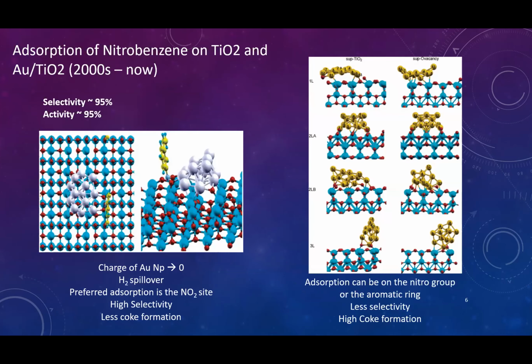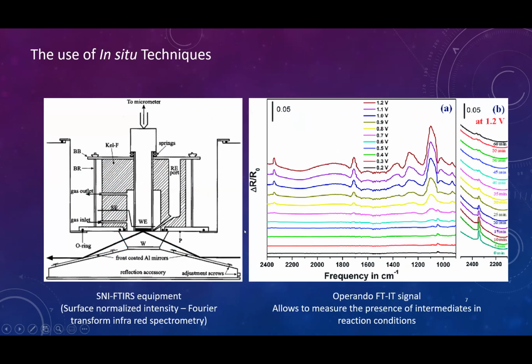So with the development of new technologies, they started using computational simulation. In this case, we can actually see how the catalyst will behave in the presence of our substrate. On the right-hand side, you see the adsorption of nitrobenzene on titanium dioxide can go through different modes, depending on whether we have oxygen vacancies or not. In any way, the adsorption can go through the ring or the nitro group. And when we add gold nanoparticles, the adsorption through the nitro group improves the selectivity and the activity. The use of in situ techniques allowed us to see the intermediates on the surface of the catalyst, so we have more information.